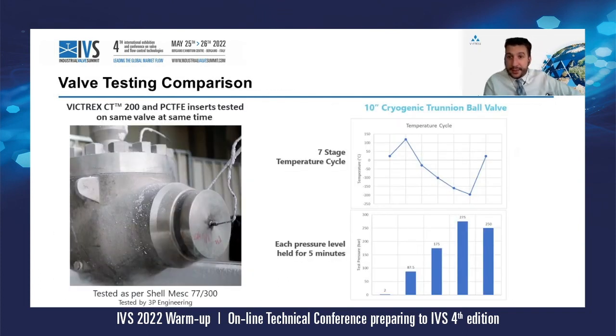After we released CT200, it was time to collect also data on its performance on field, on a real valve. So we started cooperating again with our valve manufacturers and customers to make a comparison test on a real cryogenic valve, stressing the material as much as possible, as much as we could. What you see in this slide is a significant example of testing our material in one of the most challenging conditions.